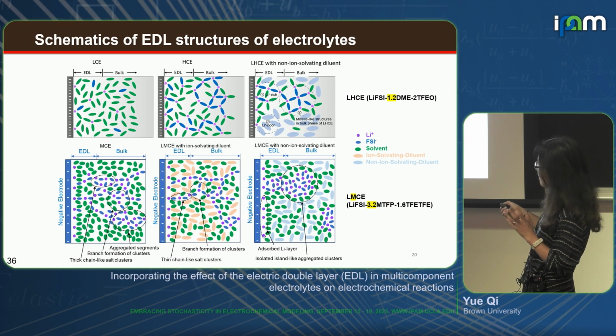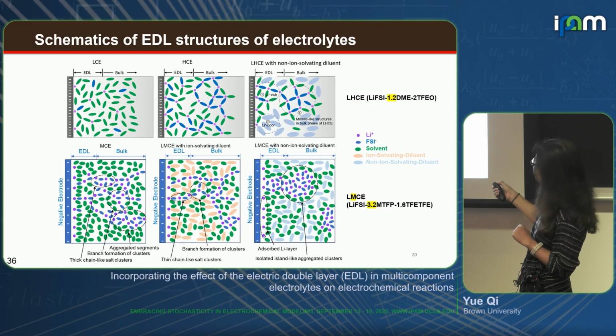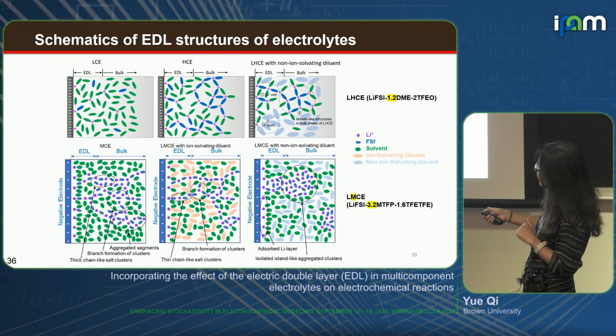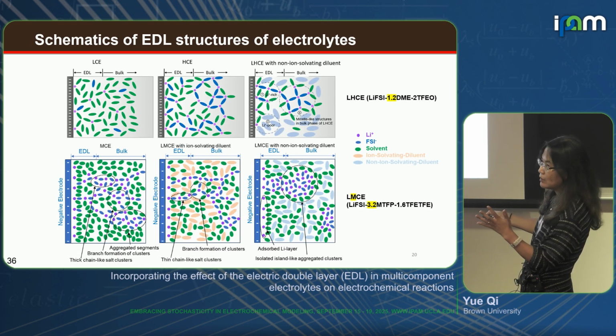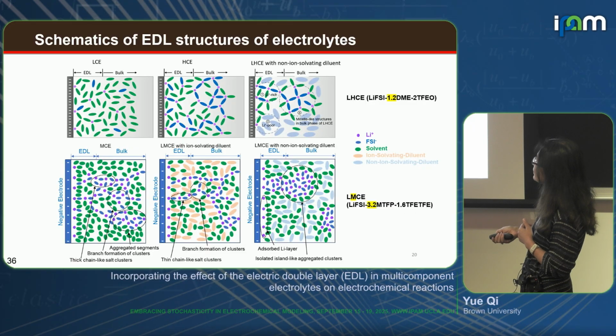Another insight obtained from the MD simulation: this is the previous one I showed you, the concentration of the salt and the solvent ratio about 1 to 1.2. And this one is about 2 molar, so a 1 to 3 ratio. And when we put this under charge, you get to see a lot of the first layers, mainly the salt clusters, aggregates, and solvent. And because we still have a lot of free solvents available here, and this one we don't, the diluent comes to the surface. And so chemistry, compositions, and interactions are all important.